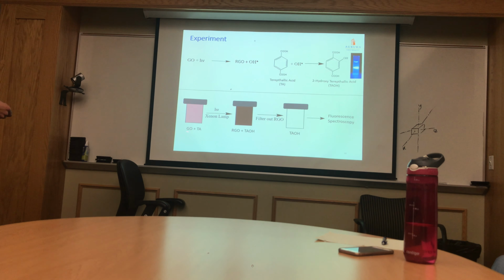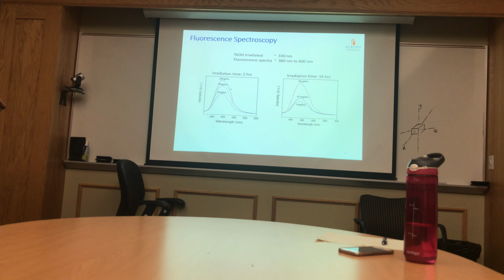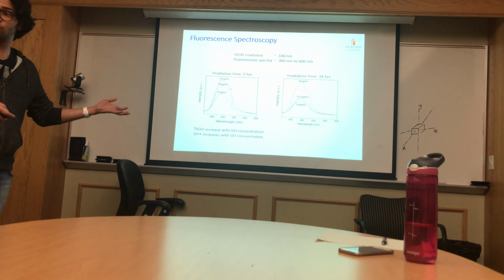Now, in the first graph, I irradiated my graphene oxide and TA samples for 2 hours, and I varied the concentration. Here I noticed that as we increase the concentration, the fluorescence increases. That means TAOH is actually produced, and the yield of TAOH is increasing as the concentration is increasing. So this proves that OH free radical actually increases with the GO concentration.